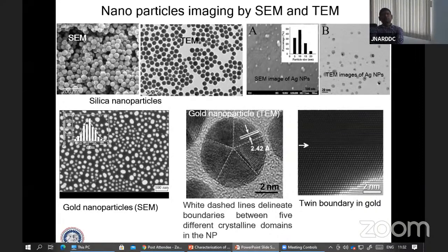And suppose you have silica nanoparticles in SEM, so you can measure by some software which is inbuilt in the SEM, and then from that you can also find out the size distribution of your nanoparticles. That means suppose your nanoparticles are in the range of 10 to 15 nanometer. That means most of your nanoparticles are in the size range of 10 to 20 nanometer or like that. So that we can calculate or analyze by the SEM.